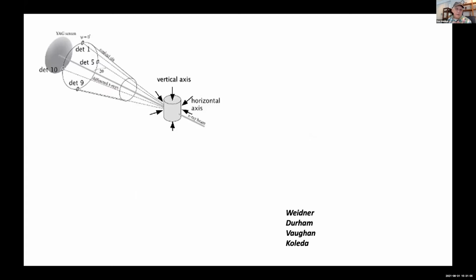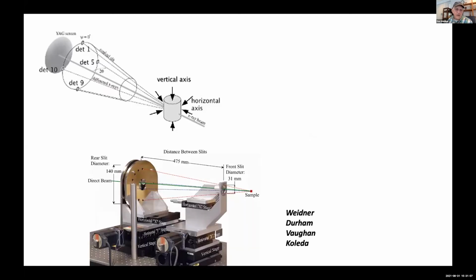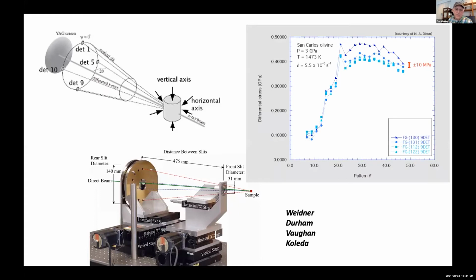Well, another picture of our conical, this is the conical slit system. And this is a deformation experiment, courtesy of Nat Dixon, from Bill Durham's group, olivine under compression. The uniaxial stress is being loaded and then the stress field moves horizontally. We concluded about a 10 MPa accuracy in the system.